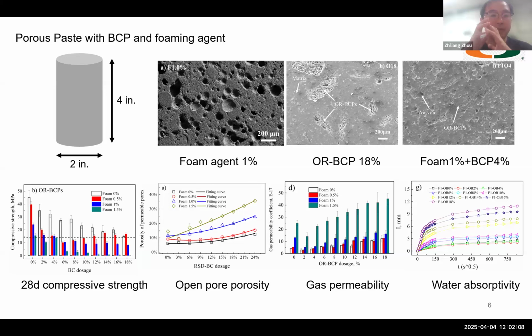At first, we mixed this biochars within the cement-based paste materials, and the foaming agent is also used to increase the porosity of cement-based materials. This page shows the physical properties of the paste samples with biochar and foaming agent. The result shows that with the biochar addition and the foaming agent addition, the compressive mechanical strength is significantly reduced, and the porosity is increased.